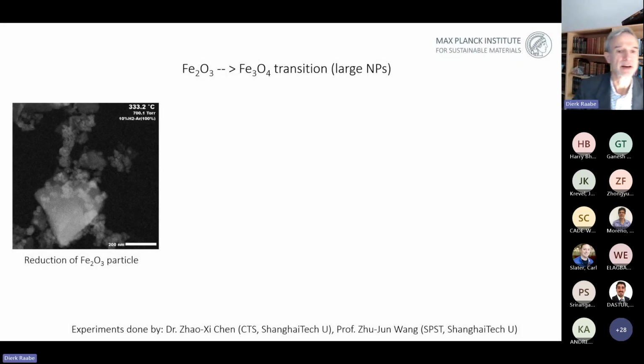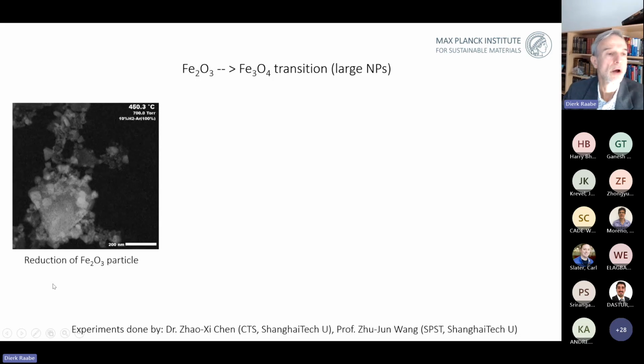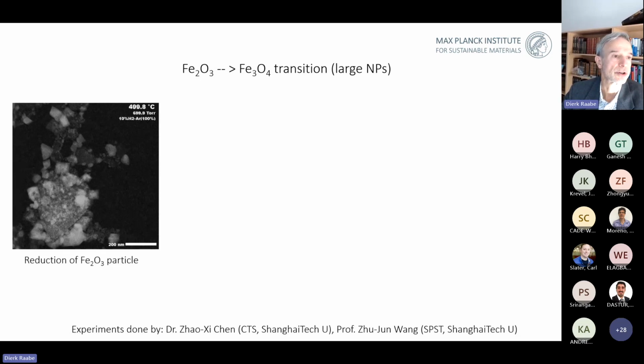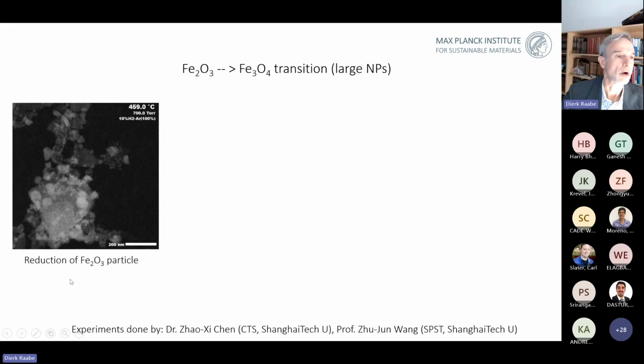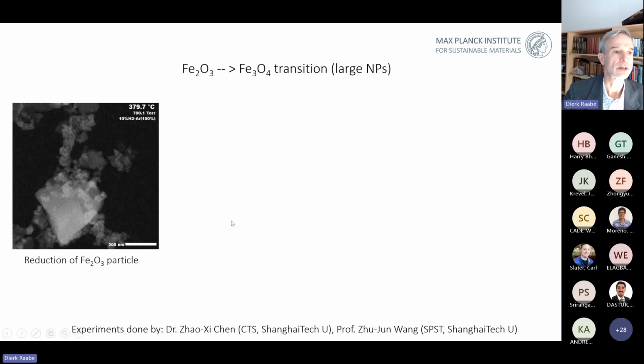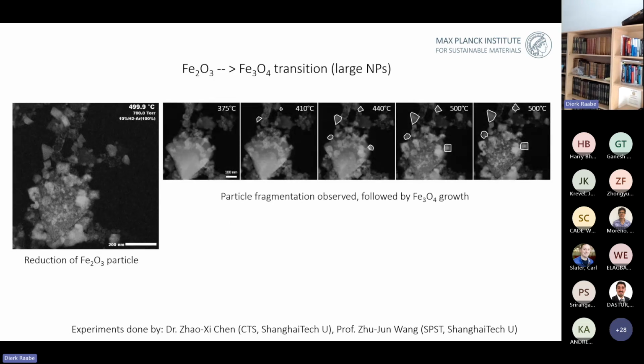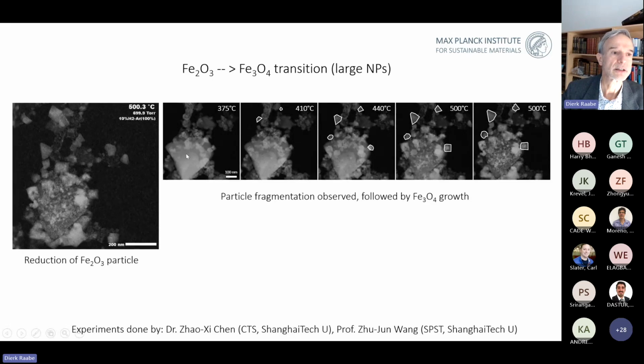Here is from our colleagues with whom we collaborate at Shanghai Tech University, Dr. Chen and Professor Wang, a very nice in situ observation with a dense solution holder where you can work under near ambient pressure conditions, here with 10% hydrogen in the holder in the early stage, namely from the transition from the hematite to the magnetite. Let me play that movie again. We are still about to analyze this in detail, but you can see there's really an explosion of these nucleation sites during this transformation. When we carve out some of the stills to show better how these patterns are evolving, you can see here as we ramp up the temperatures, how complex and how multifold the nucleation events are and how quickly you're losing the mass and open up massive porosity.